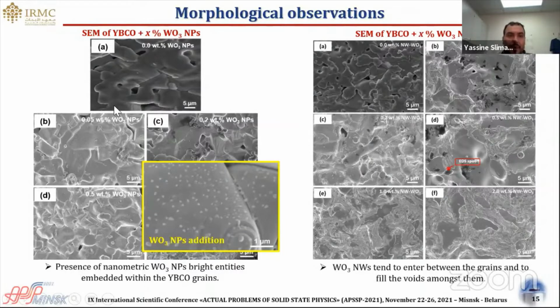For example, in the case of nanoparticle-added samples, closer looks in SEM images showed the presence of nanometric bright entities of tungsten oxide dispersed and embedded within the YBCO grain. The density of these nano entities increases with the increase of doping content.